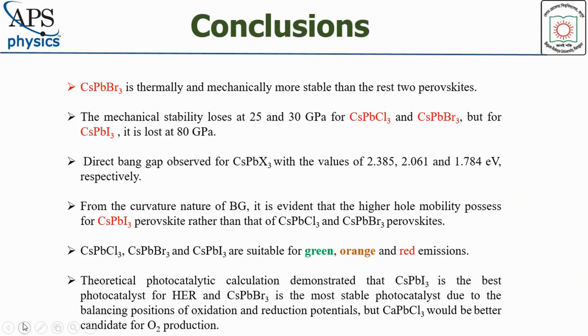The mechanical stability losses at 25 and 30 gigapascals for cesium lead chloride, cesium lead bromide, but for cesium lead iodide it is lost at 80 gigapascal. Direct bandgap observed for cesium lead halide with a value of 2.385, 2.061 and 1.784 electron volt respectively. From the curvature nature of bandgap, it is evident that the higher hole mobility possesses for cesium lead iodide perovskite rather than that of cesium lead chloride.